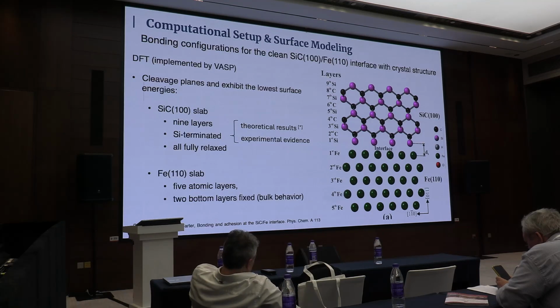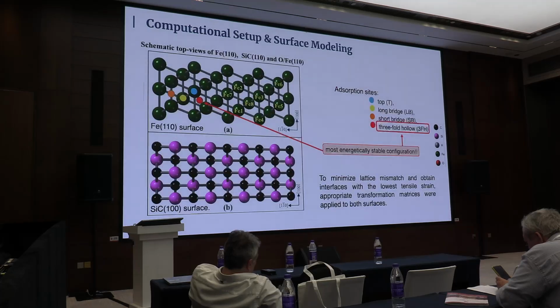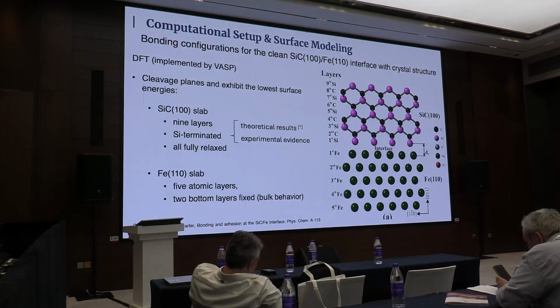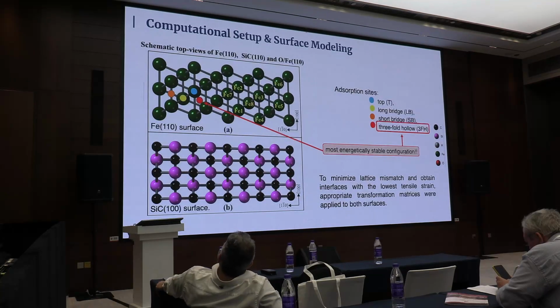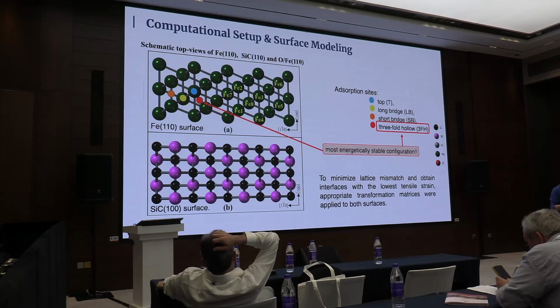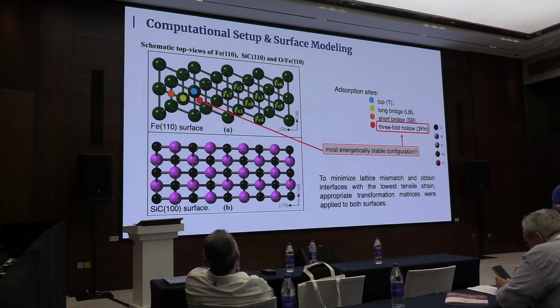And why did we choose to make a crystalline interlayer when what we really have is an amorphous one? We will come back to this in a few slides. But now it was a pure one, and we need to simulate the oxygen increase in that interlayer. Because of the way the interlayer is built, we arrive at the conclusion that the oxygen is first absorbed by the iron and then interacts with the other system.